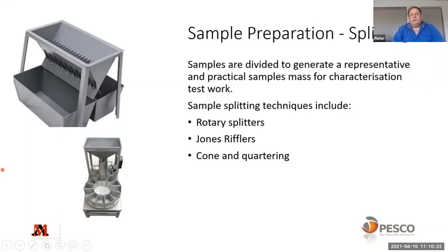Sample splitting. When you do test work in the lab, you don't want to work with a 1-ton sample, 2-ton sample. You want to work with something that's practical. So the moment you do any size reduction or sample reduction, there's also a good chance to generate error in your sampling process. So it's important that you use the right techniques when you do sample splitting. Preferable for us is a rotary splitter that we'll use to split out a big sample and generate your sub-samples, have reference samples, and you can always go back and do additional tests if required. Otherwise, you're using a jones riffler or the cone and quartering process.